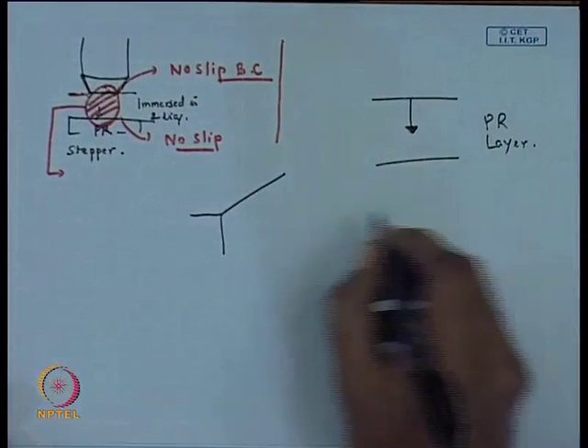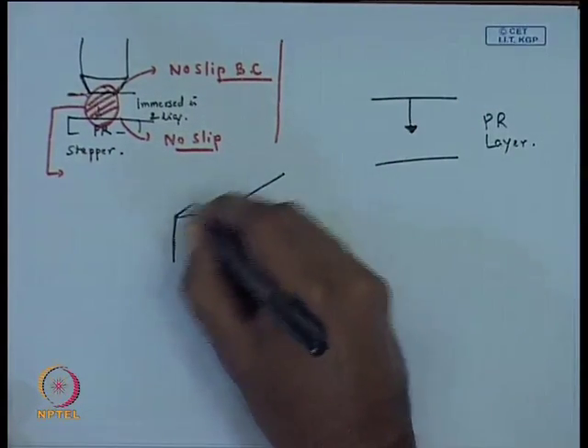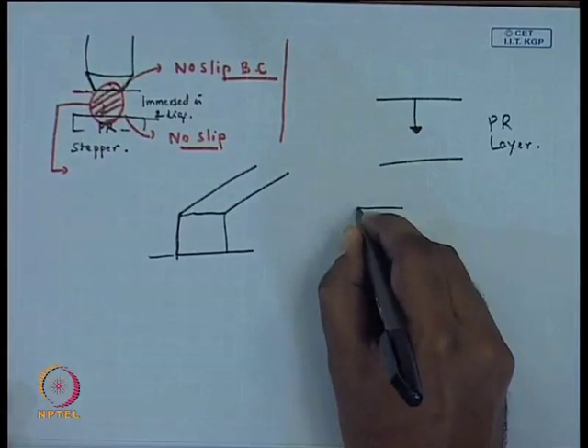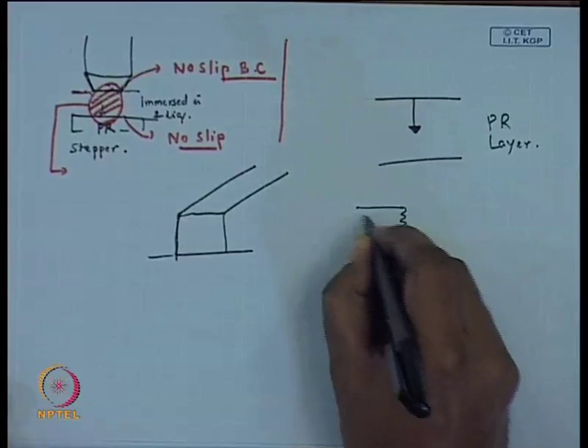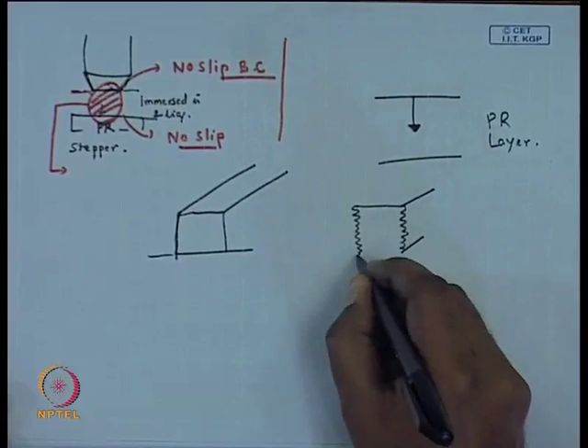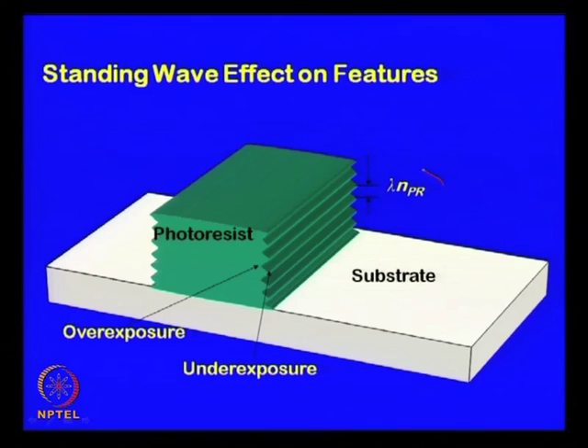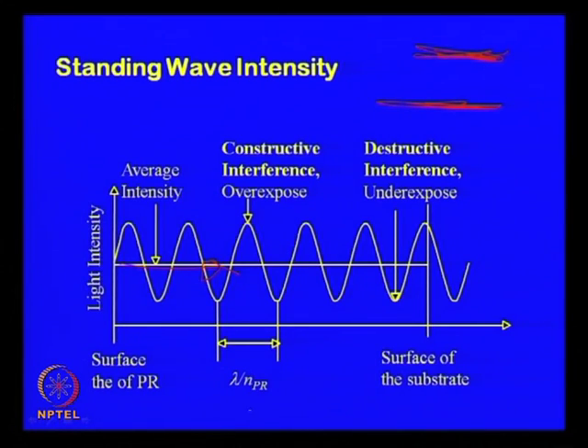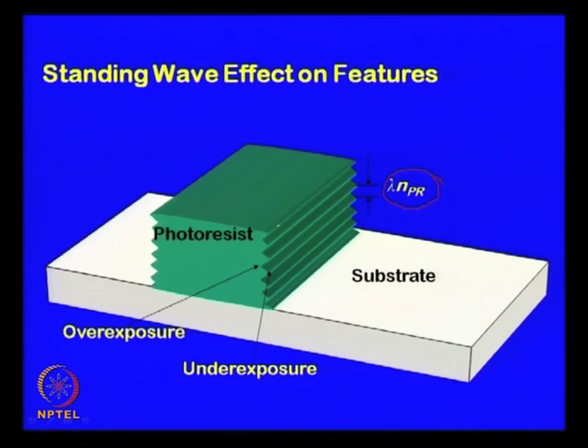However, as we have told, typically you would like to have a very sharp edge on any feature, but what you end up getting is not a feature with a sharp edge, but features like this, which is extremely detrimental from the standpoint of your application. The waviness of this standing wave feature is correlated to the lambda of the light source you are using and the interference. I am not going into the details of interference, but you can just have a look there. This is the average intensity of light, and due to constructive and destructive interference, some areas across the depth will get overexposed, some areas will get underexposed. This results in this type of standing wave effect on the features.